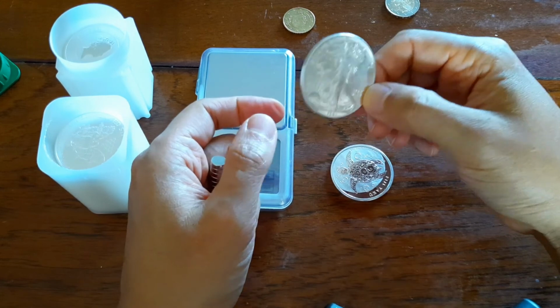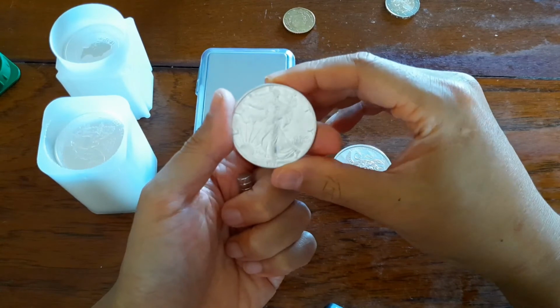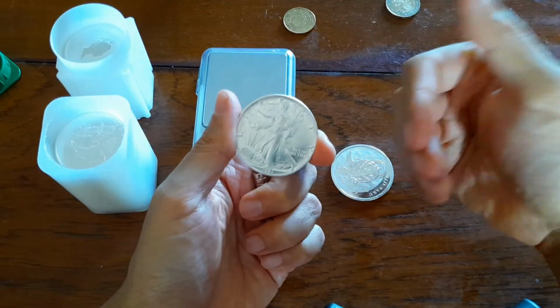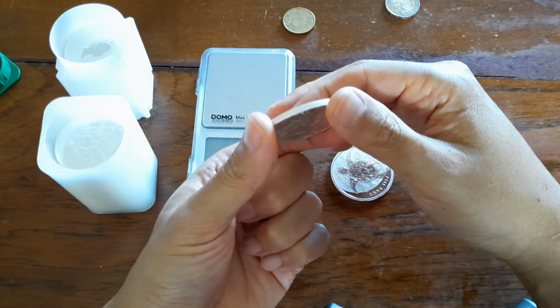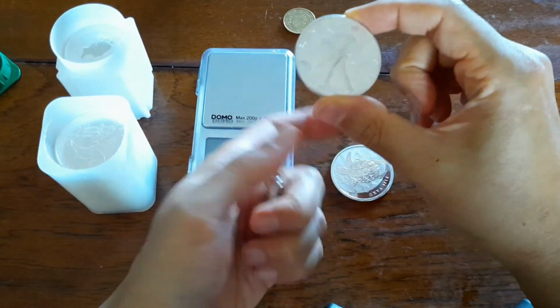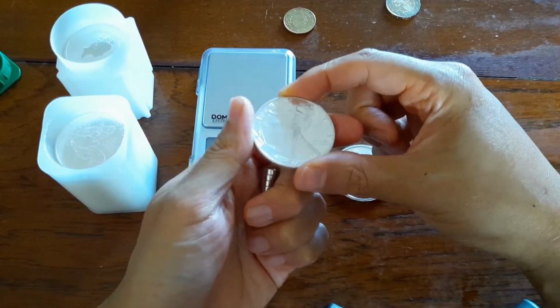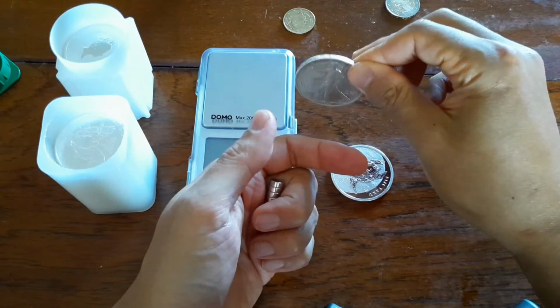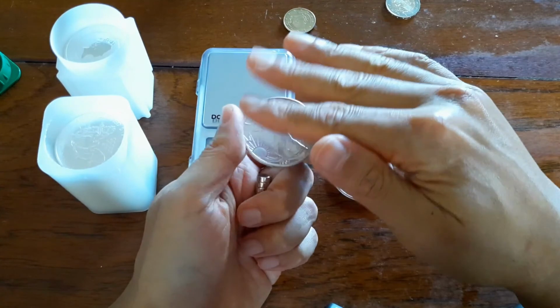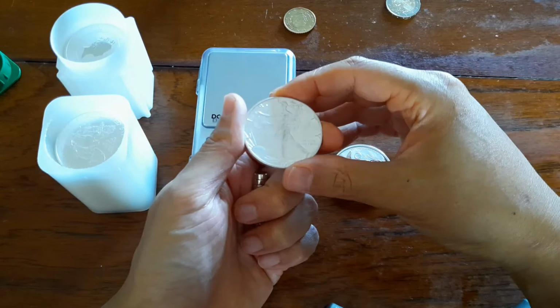But if they do super fakes where they actually get the size right and they get the density, so the weight right relative to the size, it would fool this process. The reason why I do the sound is that if somebody does a mixture between copper plates and tungsten, and then they just plate it with silver, and you get the right weight and you get somewhat of the right reading of the magnetism, and then you do the size test, it will also pass. If you do a water specific weight test, it will also pass that. But if you do a sound test, the sound properties, because it's sandwich layers, will be very different from pure silver. So that test, it will definitely fail.